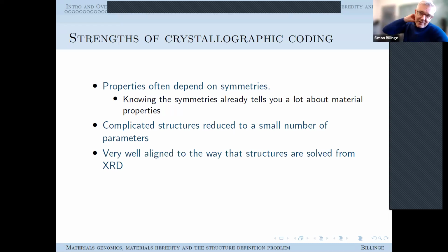Another strength of the crystallographic coding is it's extremely well aligned to the way that structures are solved. And these two went kind of hand in hand in a way. When X-ray crystallography was developed, space groups and crystallographic representations were a co-design. They grew up together. And basically, when you do an X-ray diffraction measurement, you get Bragg peaks, and the positions of the Bragg peaks tell you about the unit cell. The systematic absences of the Bragg peaks tell you about the space group.